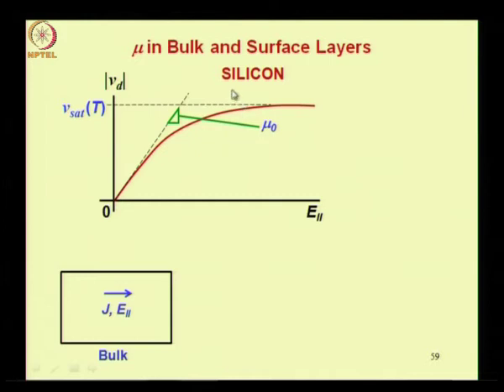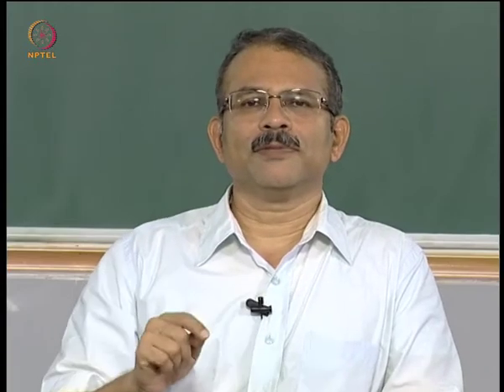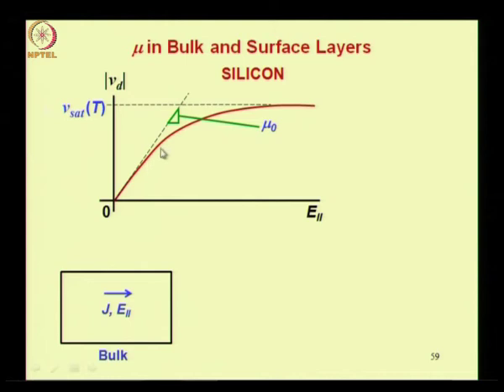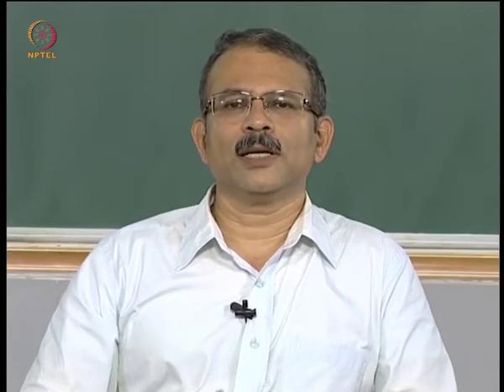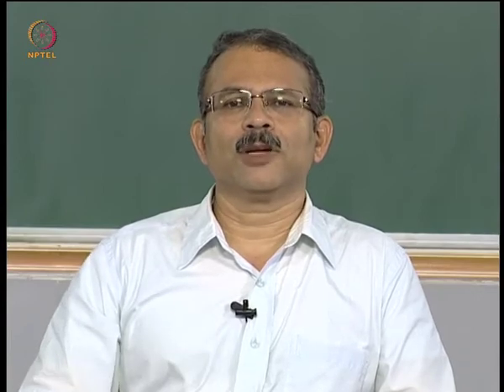Also note that we have considered a semiconductor such as silicon, for which this shape of the velocity field curve applies. For instance, for gallium arsenide we have pointed out that there is an overshoot of the velocity in the velocity field characteristics. So it would be something like this. Your velocity would go up beyond the saturation velocity, and then in some region it will fall down to the saturation velocity, showing a negative resistance region. So our description of the mobility would be related to the silicon, because the silicon devices are more prevalent. At the end we will also very briefly discuss about the gallium arsenide velocity field curve.